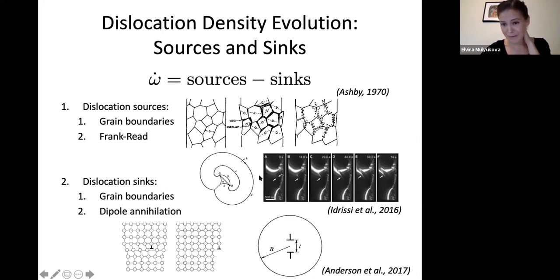And in a remarkable experiment that came out recently in 2016, Idrissi et al. actually managed to image what looks like a Frank-Read source operating in real time in olivine. I don't know how easily you can see it here, but this is a dislocation loop emanating outwards, possibly by a Frank-Read source. Quite an achievement, because imaging dislocation motion in real time is quite a challenge.